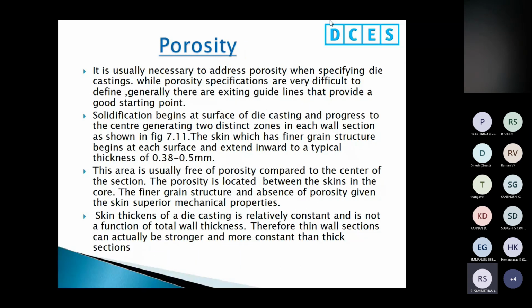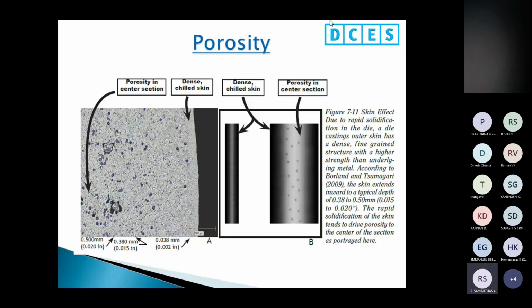Porosity. This is a very major issue in diecasting. We will discuss porosity more elaborately. It is usually necessary to address porosity when specifying the diecasting. While porosity specifications are very difficult to define, generally there are existing guidelines that provide a good starting point. Solidification begins at the surface of the diecasting and progresses to the center, generating 2 distinct zones in each wall section as shown in figure 7-11. You see, there is a porosity in the center area.